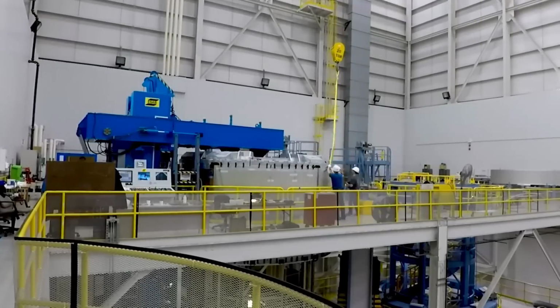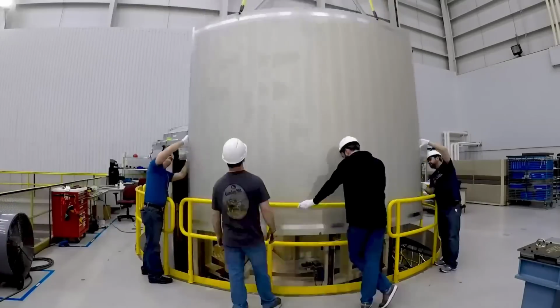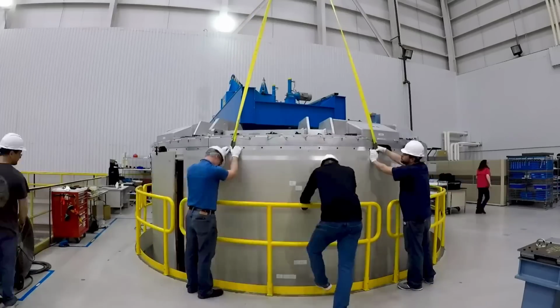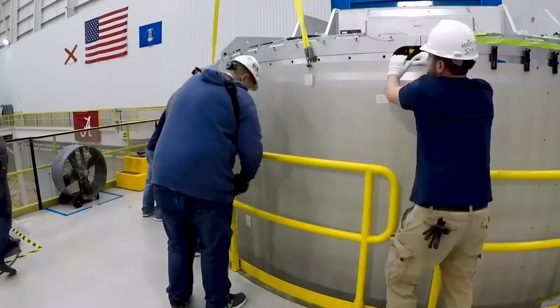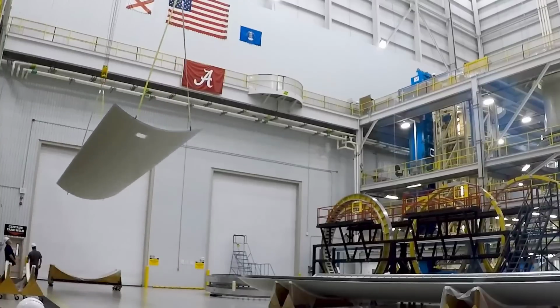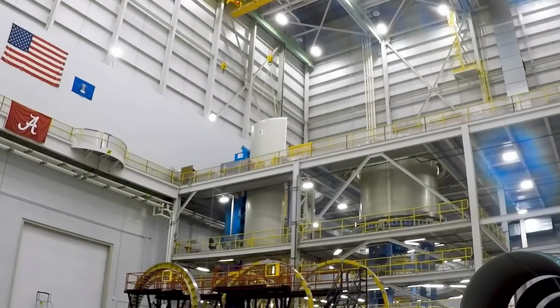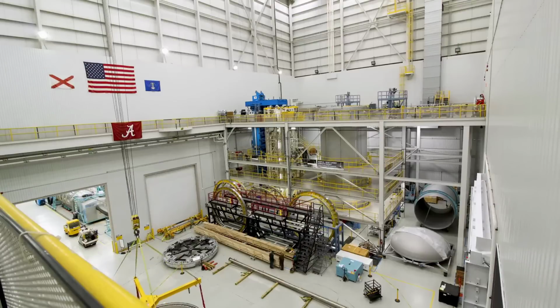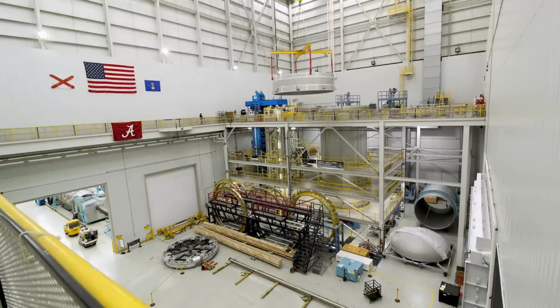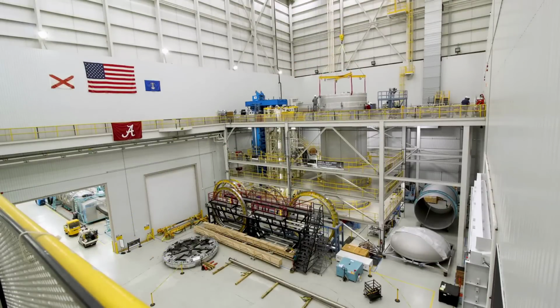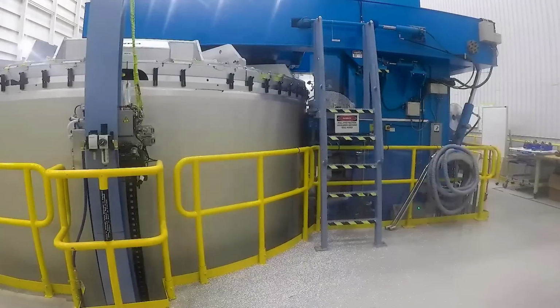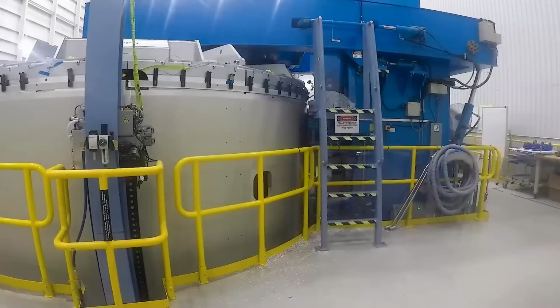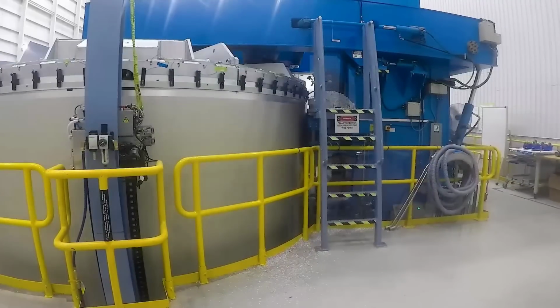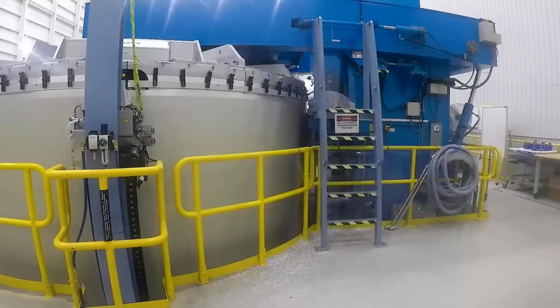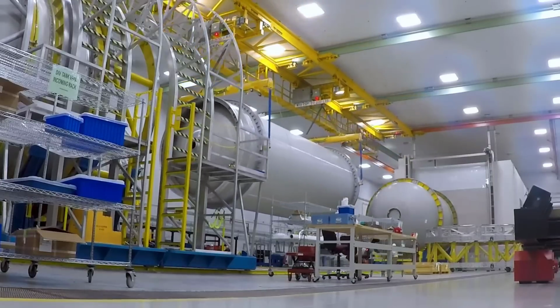The next stage involves the transformation of these panels into the essential barrel sections of the fuel tanks. This is achieved through precise bending and pressing in the brake form and bump press, creating the curved radius required for the fuel tank construction. The barrel sections are then subjected to friction stir welding, a distinctive process employing frictional heat and stirring of the parent material to form an exceptionally strong welded joint. Remarkably, this process doesn't utilize any filler material, contributing to the integrity and robustness of the final product.